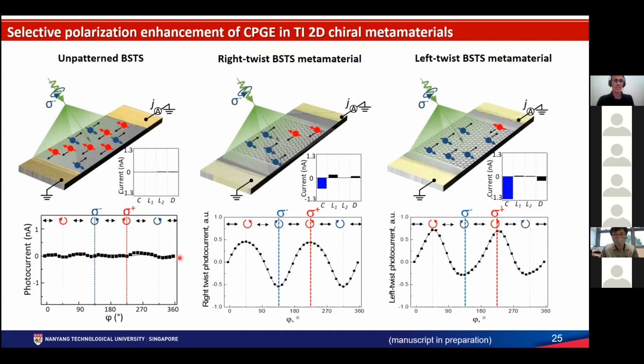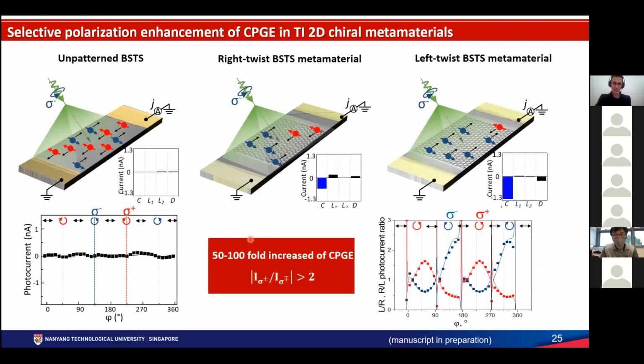You see a small wiggling. But now when you come with either the right twist metamaterial or the left twist metamaterial, you see a reversal of the effect. And this becomes more clear when you actually take a ratio between the two.